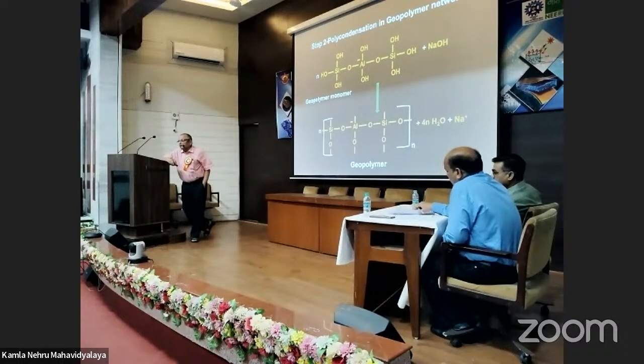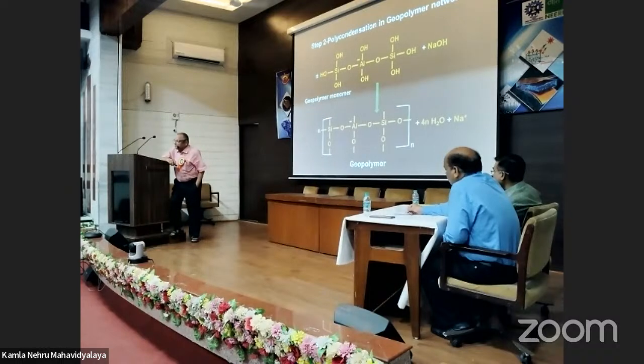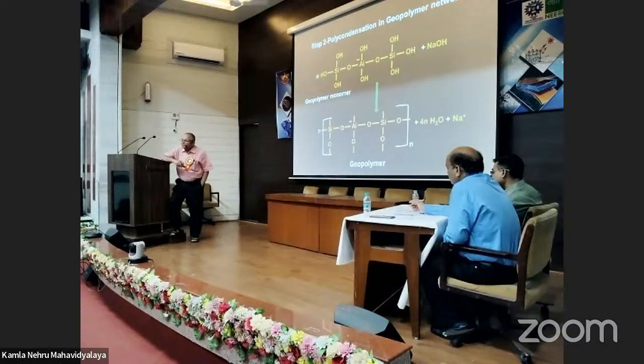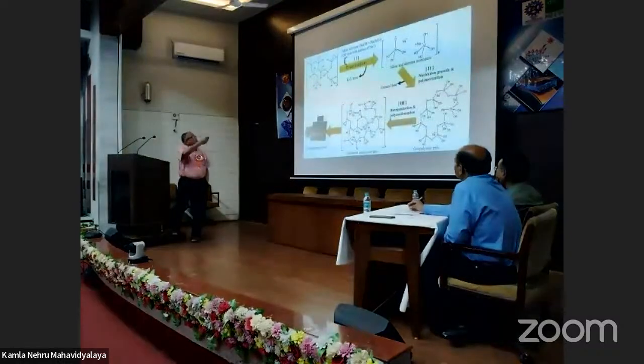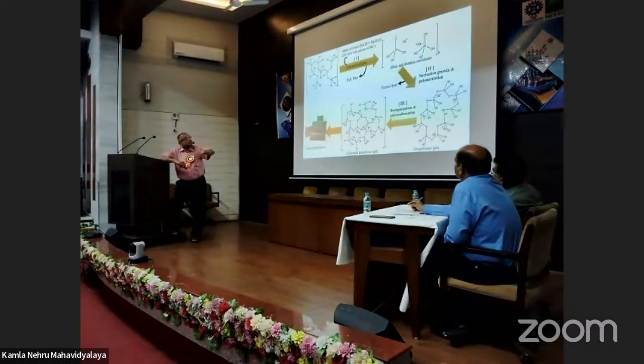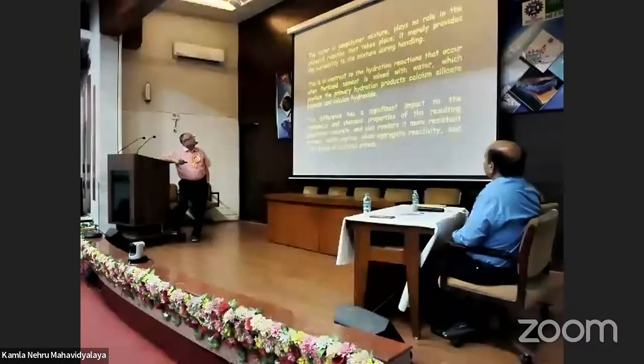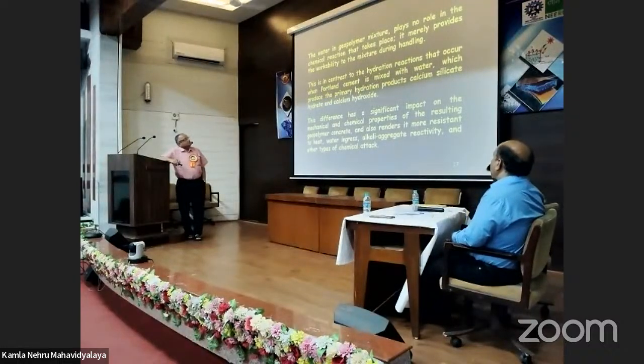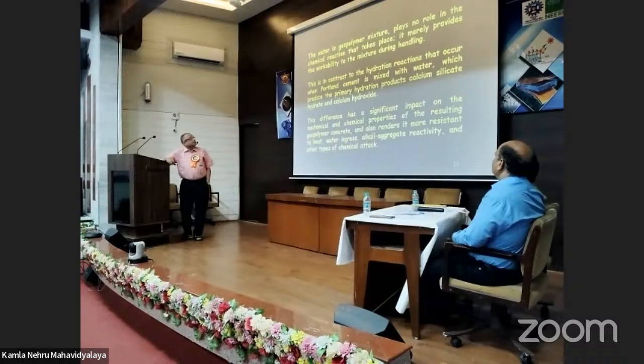water is eliminated. Now, one basic difference between Portland cement hydration and geopolymer formation is that in cement hydration, water is consumed, whereas in the formation of geopolymer, water is eliminated. Water can facilitate the process of reaction. Now here you see the structural features, how the dissolution, silica and alumina are there, the same structural forms are shown here. The water in the geopolymer mixture plays no role in the chemical reaction that takes place. It merely provides the workability to the mixture during handling.